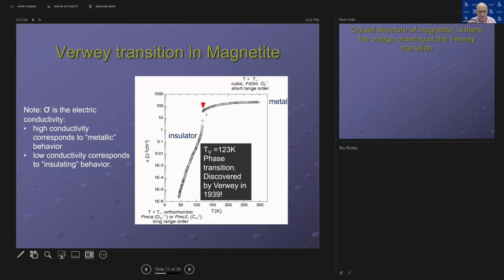So what you can see here is that above around 120 Kelvin, the material is not a bad conductor. But then at 120 Kelvin, the conductivity of the material drops. And this is a logarithmic scale, so the drop is 2 orders of magnitude. Had I drawn it on a linear scale, that would be just a very sharp step. That just shows how things change at the lower values of conductivity. So there is this transition between a metallic state and an insulating state, and the mechanism of this transition was something that was interesting to me.